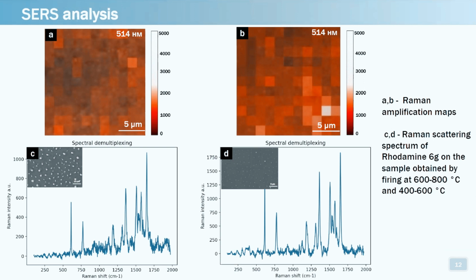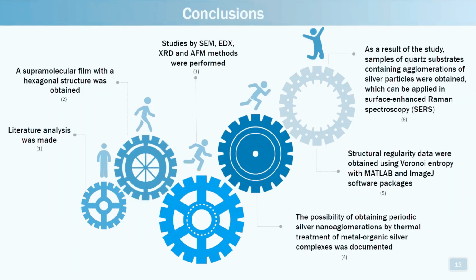The sample that was obtained at lower temperatures represents the structure that has intensity approximately 75% higher than at higher temperature. This effect could be explained by the fact that metal nanoparticles of smaller size contribute more to the SERS effect because of high concentration of surface plasmons.